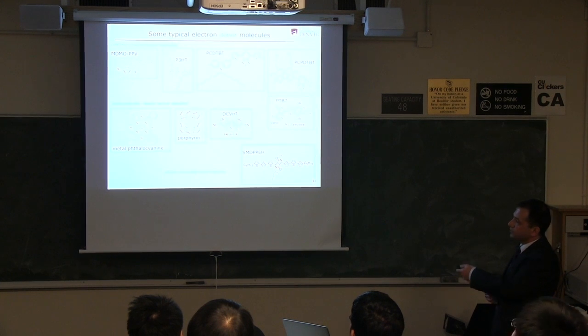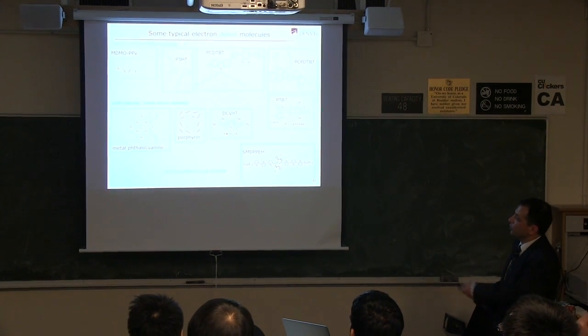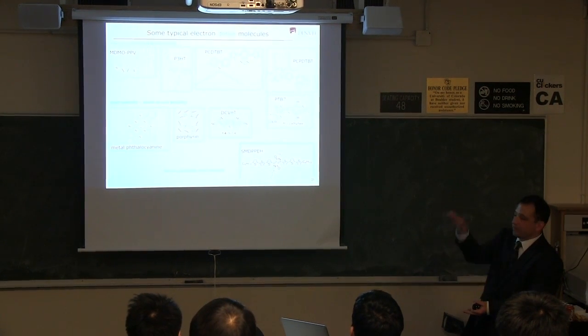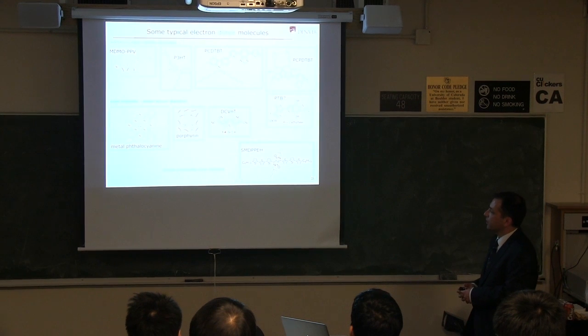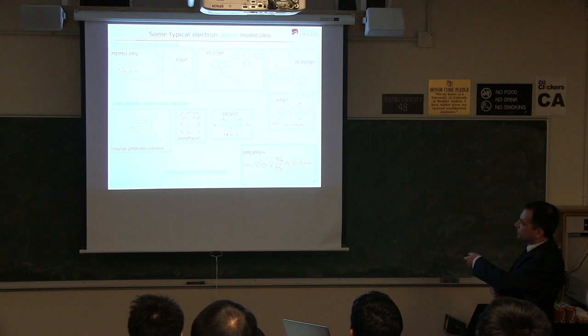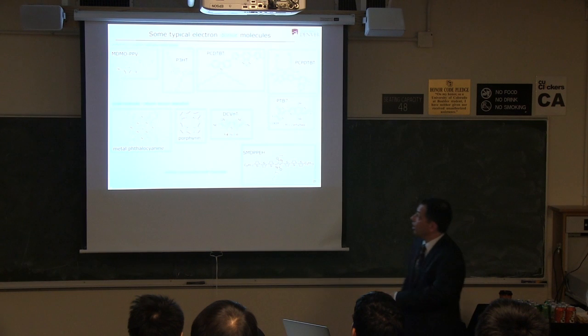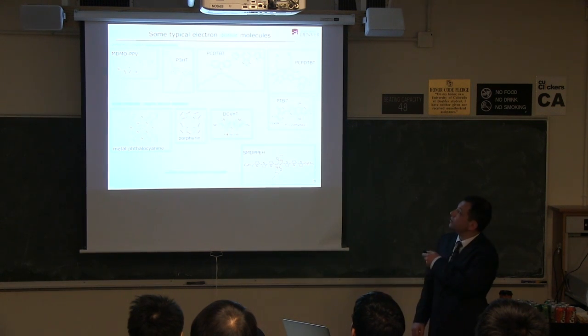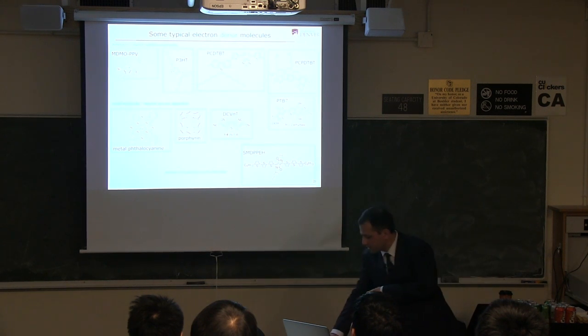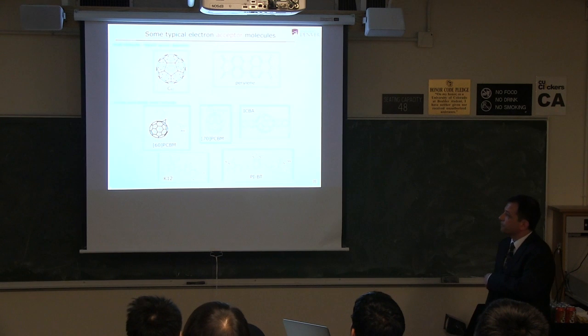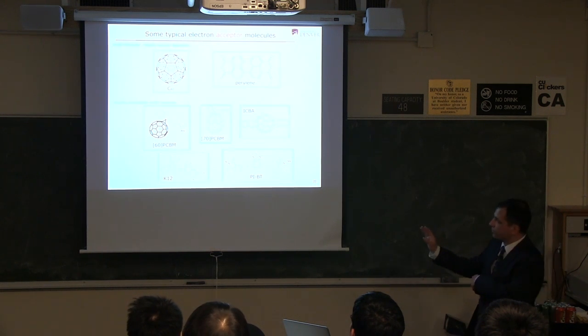Those are all polymeric materials in blue. We also have vacuum deposited materials that don't have these long linker chains on the side, so you can heat them up and they won't crack, and they will sublime onto a device substrate. We can also have materials that are low molecular weight, not polymers, that we dissolve in solution. Those are solution processable small molecules. Now all of these types of materials are donor materials. They're electron donors, which means they're basically p-type. We need on the other side some n-type. Those are electron acceptors. The variety of these molecules is a lot less.